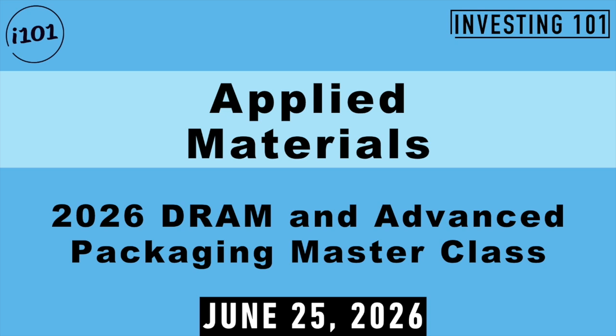Next, selective epitaxy is used to form the lateral transistor junctions and storage node contacts. This epitaxy step is especially challenging because it is non-line of sight and must be uniform across hundreds of layers. Applied's Centura Prime Epi system is tuned for highly selective deposition and leaves no unwanted metal that could create shorts in buried structures that cannot be accessed or repaired. Finally, selective ALD deposition of a metal such as molybdenum silicide forms low resistance contacts across all the layers. Lateral selective deposition is challenging, and plasma energy cannot be used because ions travel directionally. So thermal processes must be used instead. And the selective ALD moly technology we developed for the foundry logic market can be used in this 3D DRAM application.